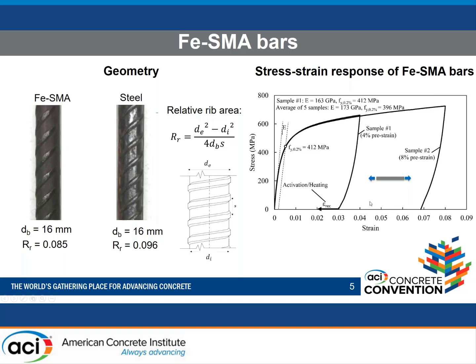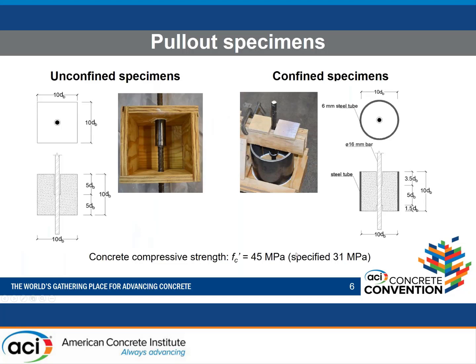Here I'm showing the stress strain plots for the SMA bars for 4% pre-strain and for 8% pre-strain. And here we are showing the strain recovered upon heat activation. We were able to get 1% strain recovery. Here you can see the yield strength of the material and the modulus of elasticity. This is very close to conventional steel, while the modulus of elasticity is smaller than conventional steel. This corresponds to around 24,000 KSI. So this is the material, and now these are the specimens.